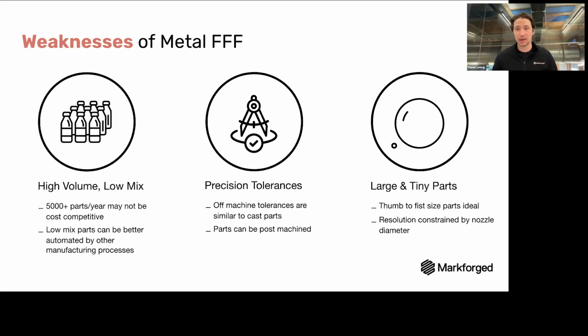You can go larger depending on the part, but generally that's the top end of the size constraint. And the bottom end of the size constraint is basically due to the nozzle. When you're printing with the nozzle, your feature size is constrained by the diameter of your nozzle, versus 400 micron. So printing features smaller than 400 micron minus 20% for the shrinkage factor is really difficult. Those are the things where we see the edges of the system. At the end of the day, there is a wide variety of parts between those sizes, but a lot of people have parts that need to be larger or smaller, and those are parts that are just not optimized for the system.